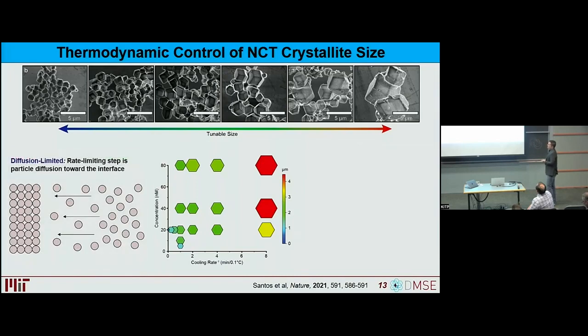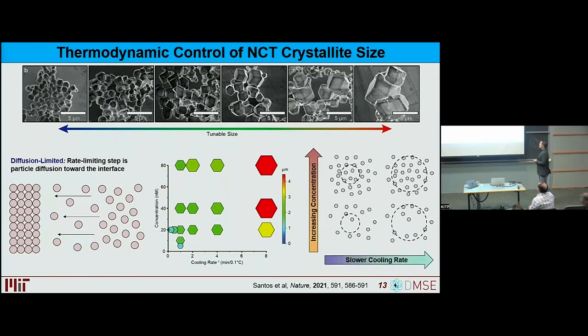Well, the answer is that this is a diffusion-limited process. Compared to a traditional atomic crystalline growth, we're working at way lower concentrations, and the diffusion of the particles is significantly slower. Meaning that what's really going on here is not standard classical nucleation theory-dominated processes, but rather what we have is sort of a diffusion-limited process. So briefly to explain that, essentially what's going on is there is a certain time window in which a particle can actually diffuse into and become part of a growing crystallite. Now that defines a certain volume around that nucleus. Basically, if a particle is within that volume, it should be able to reach the nucleus and become part of it as it grows. But if it's outside of that, it is more likely on that time scale to actually find a different nucleus and become part of that.